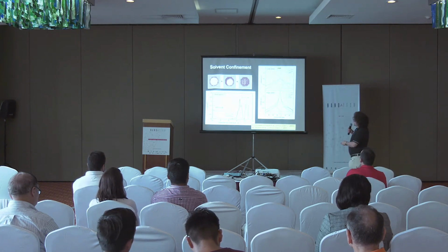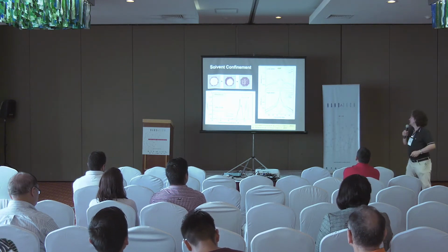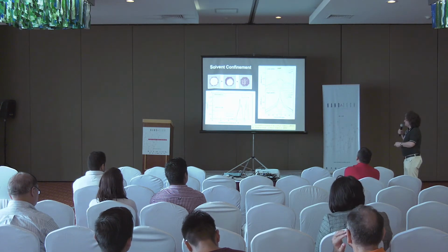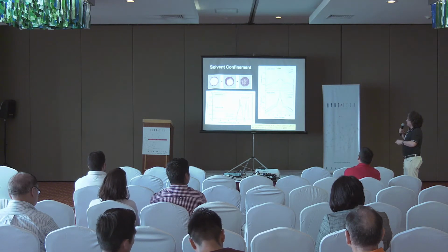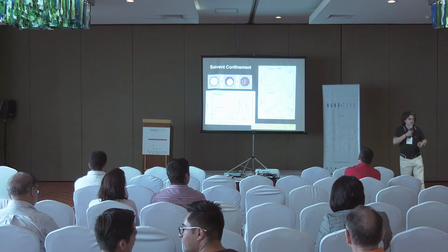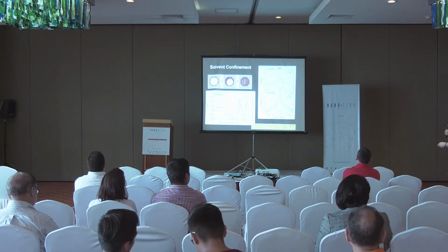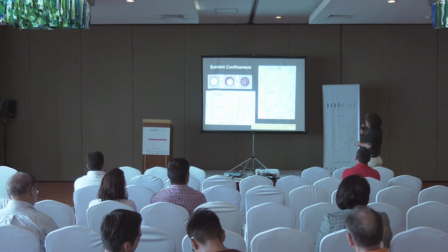This is the density, computed density. We made molecular dynamics experiments, and you see the computed density here from the pore center to the pore edge. And what you see here in the blue and red curves is that when you have very little water in contact with this material, the water adsorbs on the walls. But there's something very interesting here.